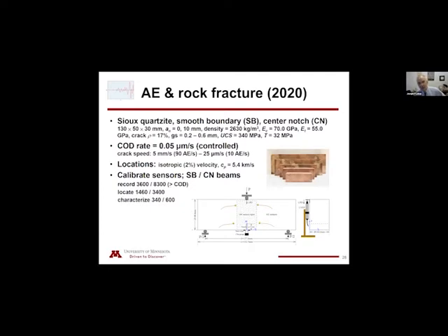We've calibrated the sensors and just some numbers in terms of events. So the smooth boundary, 3,600, the center notch beam, because we went to a larger crack opening displacement, about twice that number. We can locate more of them, but this is within a certain error, so 1.5 millimeter error, and we're able to characterize, again, within a certain error, and I'll show you how we define that for these numbers. Again, the geometry, some of the beams, we do have DIC, but I won't be showing those results. So only results related to AE, as well as, of course, mechanical response.